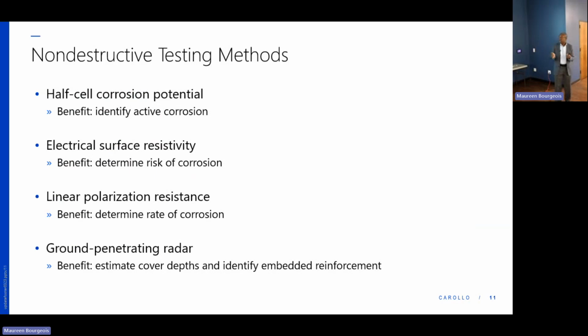What is the purpose of it and why do we want to do it? For the half-cell corrosion potential, for example, it helps us identify, is there active corrosion taking place? So we'll get a reading. And from that reading, we're able to interpret whether there's some active corrosion taking place behind the concrete that we cannot see. Electrical surface resistivity also determines the risk of corrosion. What are some things that are taking place behind when we put the equipment there to give us that data, and we're able to read that. Linear polarization determines the rate of corrosion. How fast is this thing corroding? And that equipment is also able to give us that data.